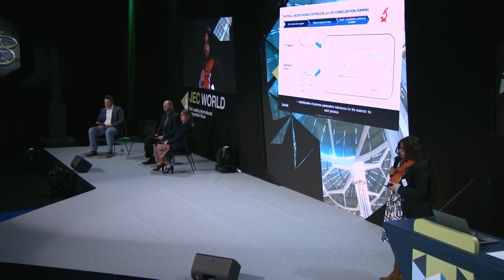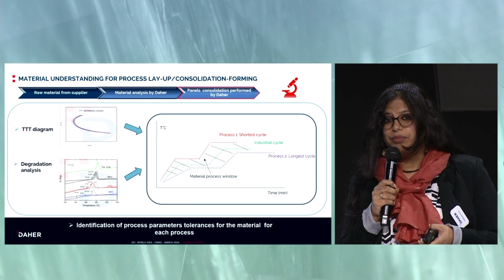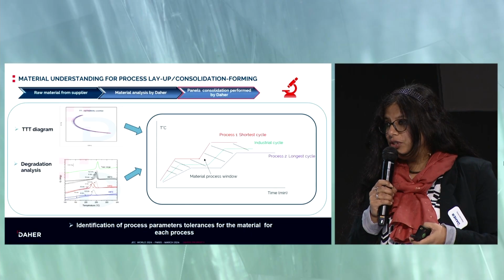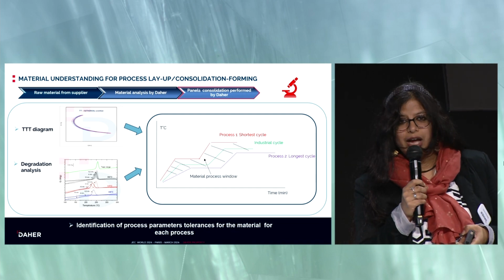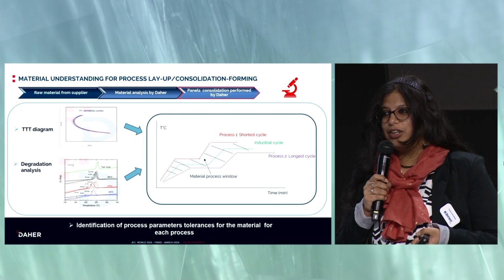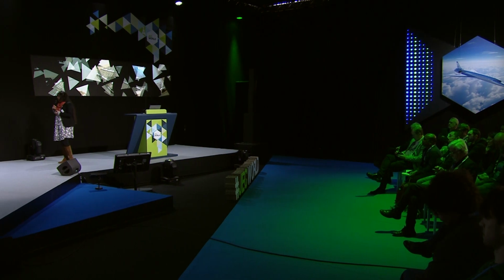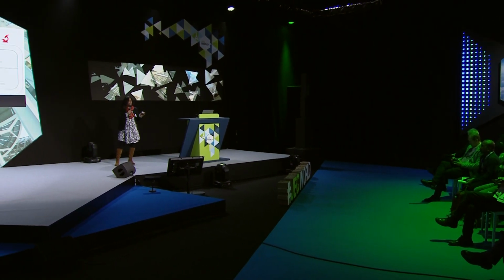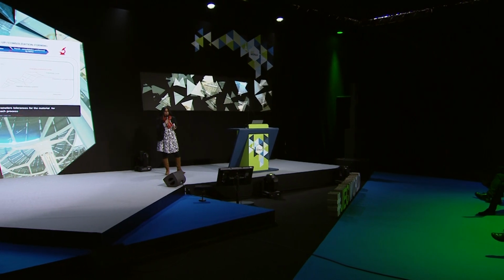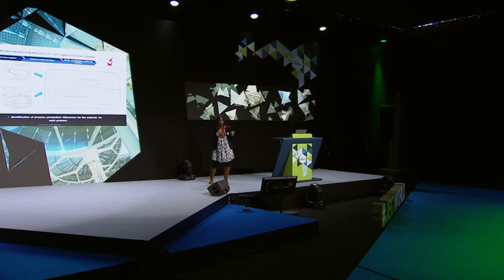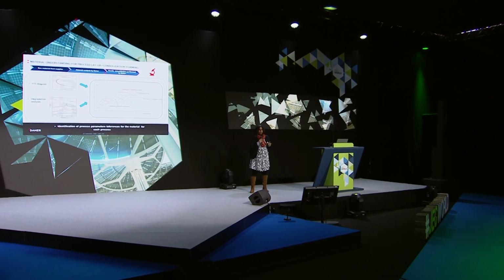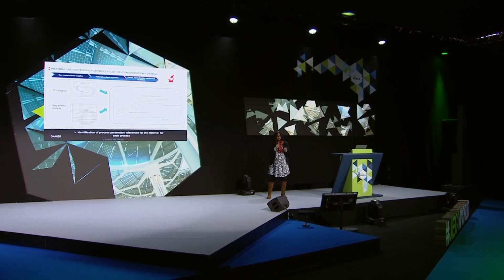We have the TTT diagram, and we have also done some DSC analysis at high temperature, at different temperatures and different times, to see if there is any degradation of the material. And we have the shift that you can see down on the picture. There is a shift of the peak, which means that there is a degradation of the material. So if we understand the TTT diagram and when there is a degradation, we can have a process window for the material, for the parts, that we can give to the manufacturer to help us to have the parts correctly done, with serial production in control.